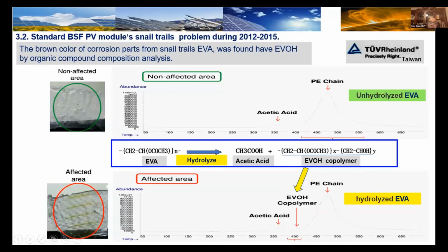So they also checked the EVA itself. They did some analysis by organic compound composition analysis. They compared the non-affected area, the no snail trails area, with the snail trails area. They found it's only a small part that is different here. This is a peak from EVOH. Where does the EVOH polymer come from? It comes from the EVA hydrolyzed. So that means in these affected areas the EVA has already hydrolyzed. When hydrolyzed, they have the acid and the EVOH polymer. So here you can see the peak. So at this position, their EVA already changed, okay?